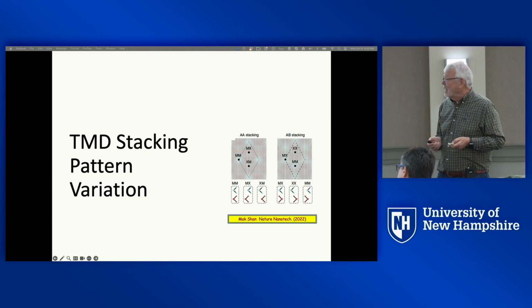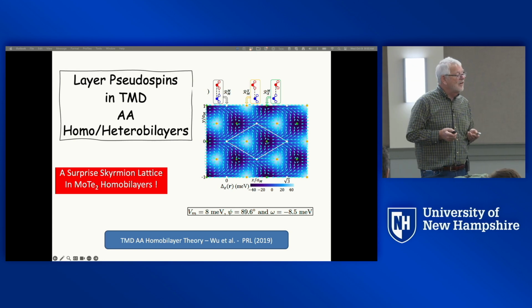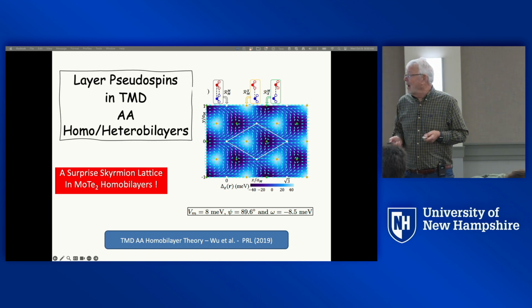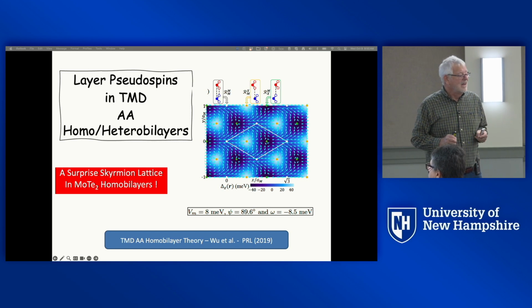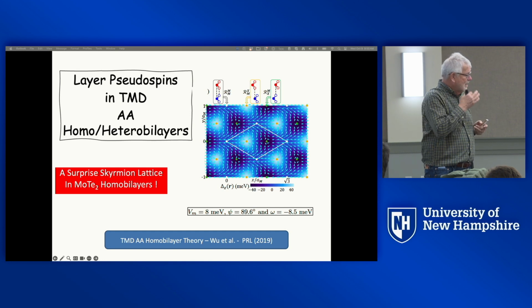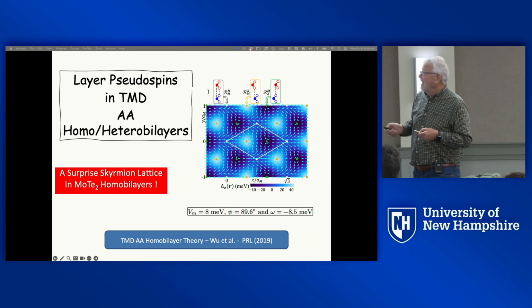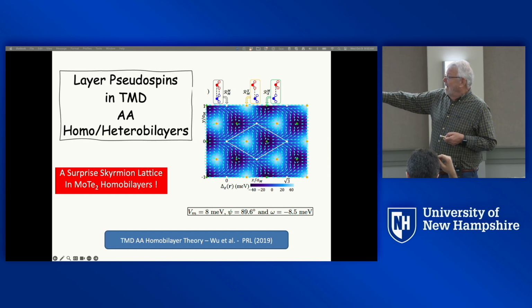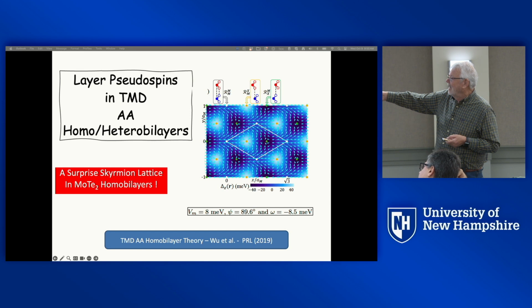The Hamiltonian is actually layer dependent, and the tunneling terms between layers are very similar to the ones I discussed in the graphene system. If I look at the tunneling Hamiltonian and think about the layer degree of freedom as a spin-like degree of freedom, a two-level system, then in these Moiré patterns, it turns out that at the chalcogen and metal-on-chalcogen positions, the tunneling between the layers in this local approximation vanishes.